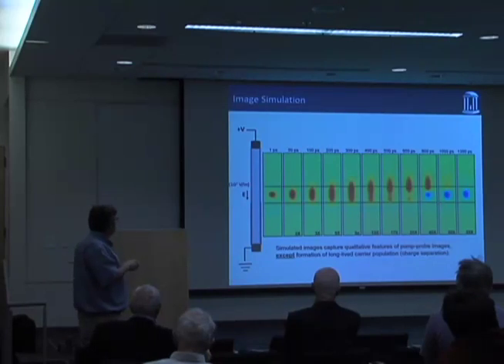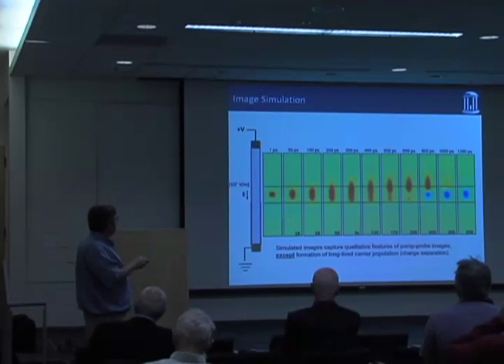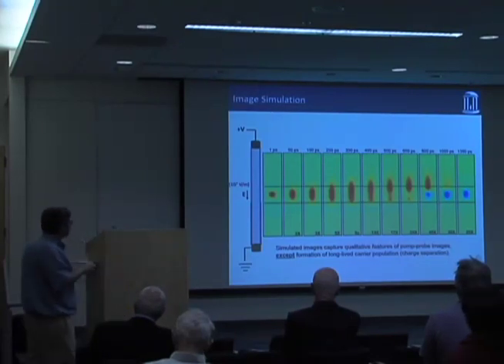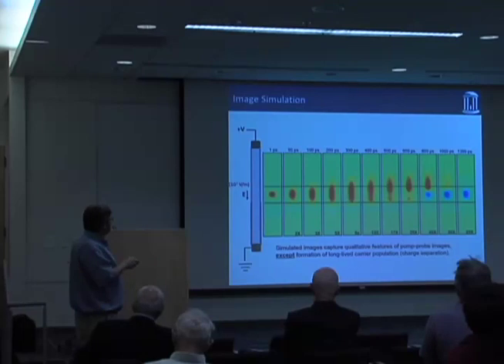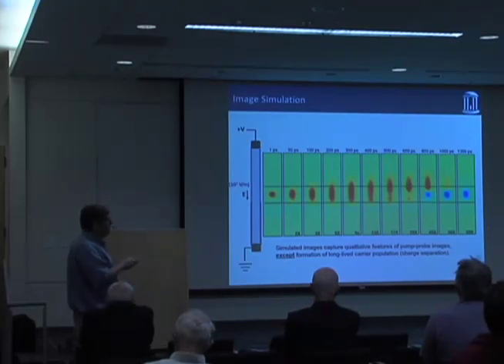It's kind of like a little black hole. As soon as things go in there, they're gone. But in the N-type region, the carriers spill into it, and then they decay over hundreds of picoseconds out to about a nanosecond or so. What we don't see in the simulation is any intensity out here at really long times.